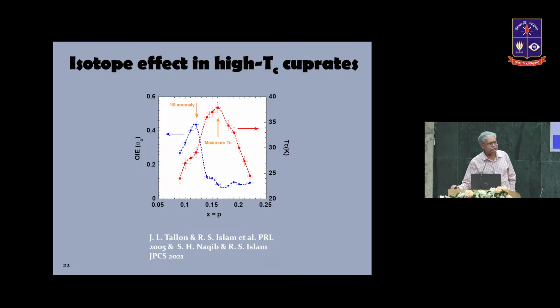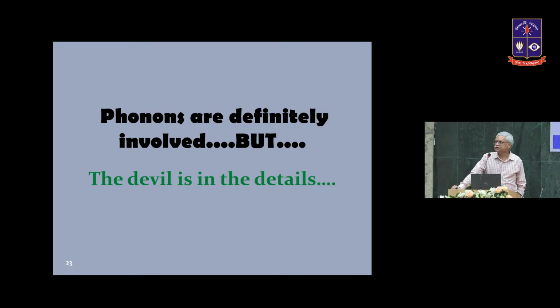Since we see an isotope effect, we have to admit that phonons are involved. But to what extent, that is the question. Because you have a huge isotope effect, a very large electron phonon coupling constant on the underdoped side, but the superconductivity is very weak. Now, this is not the ordinary BCS picture. There is something serious going on there, and it is not conventional.